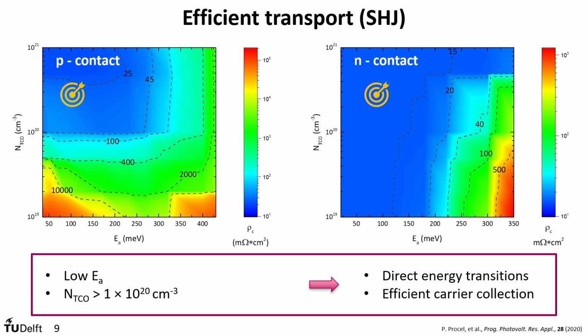Now, what I would like to postulate is that, of course, when we go to low activation energy material, you cannot do it with any type of materials. Essentially, you need to go into a nanocrystalline type of regime for your plasmas, and also look into relatively wide bandgap materials, because in this way the activation energy can be minimized, because the bandgap of this doped layer can essentially include a higher band bending at the interface with crystalline silicon across the intrinsic amorphous silicon.